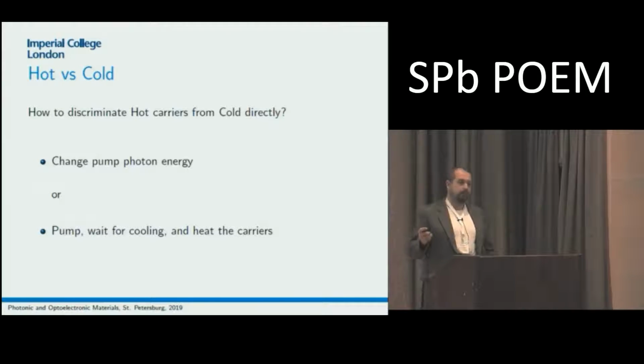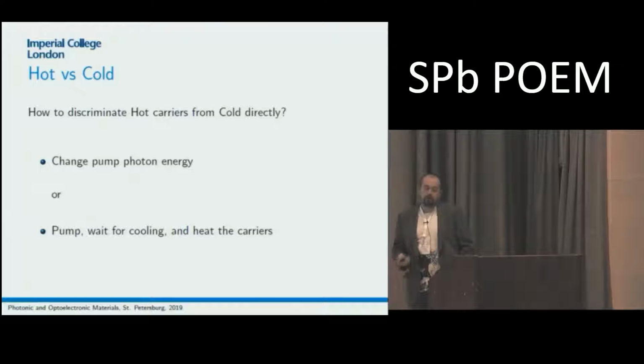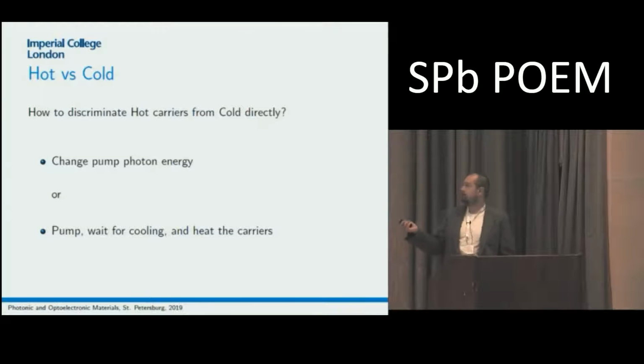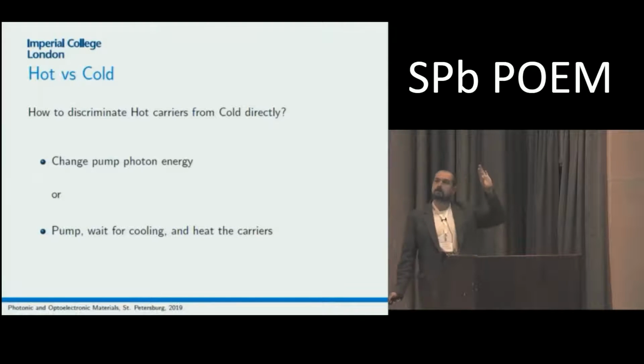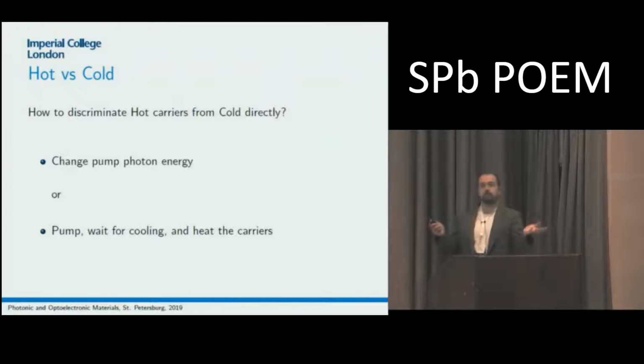Just a little bit more about further steps that can be taken. We've recently published some results on direct measurement of hot carrier dynamics and hot carrier cooling in perovskites. What we do is, we don't change the pump photon energy. We pump with excess energy, then we wait for some time until the carriers thermalize, and then we use an extra infrared pulse to perform intraband heating of these carriers. And then we measure the change of transmission.